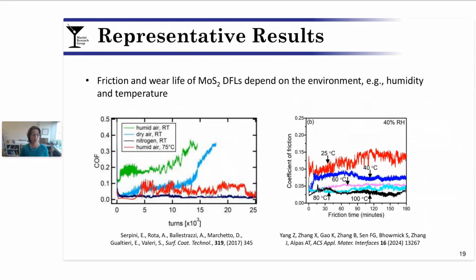So let's look at some representative results. What I'm showing you here are two plots of the friction coefficient as a function of either cycles or time from the literature. On the left, I'll bring your attention to comparing the green line and the purple line. The green line was tested at room temperature in humid air, and the purple line at room temperature in dry nitrogen. And what you can see right away is that the performance is far better with the purple data set, where we have no oxygen and humidity. And when I say better, I mean lower friction coefficient and longer wear life.